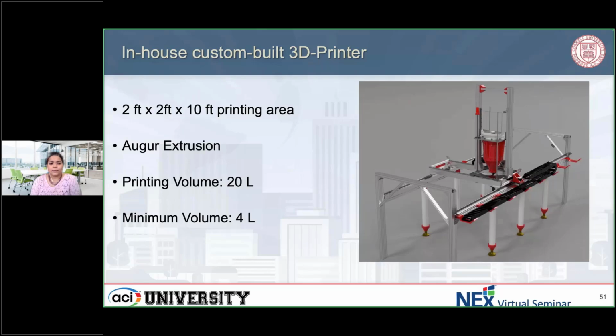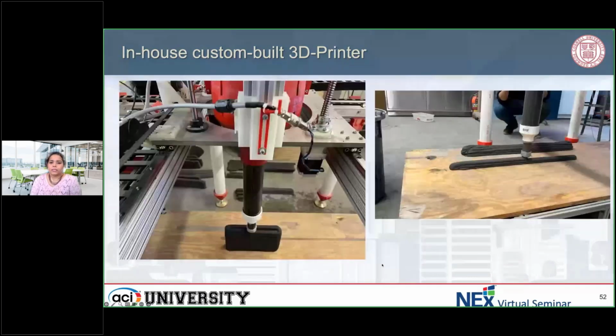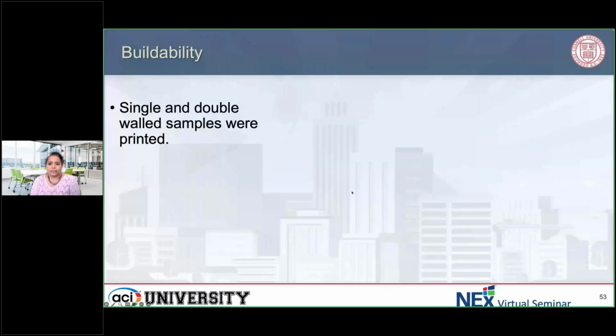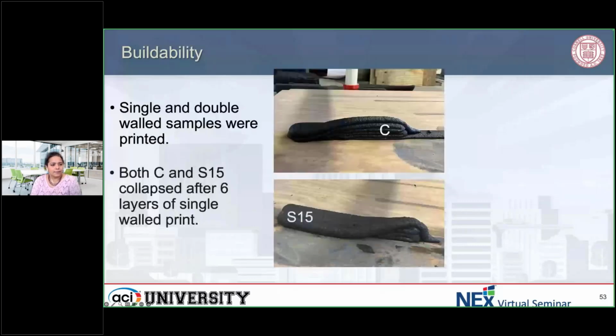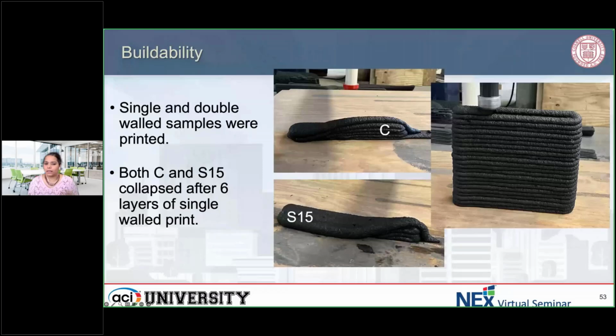So as you can see over here, we are able to do the layer by layer extrusion, and we are able to make the printer go where we need it to go. So it definitely works, and we're able to do these buildability tests. So we printed both single walls and double walls. So this is like a single wall system. So the C is the control, and S15 is with 15% of SPR inside the mix. And you can see both of them collapsed at about 6 layers. But when you print a double wall, because it's more structurally stable, you're able to build more